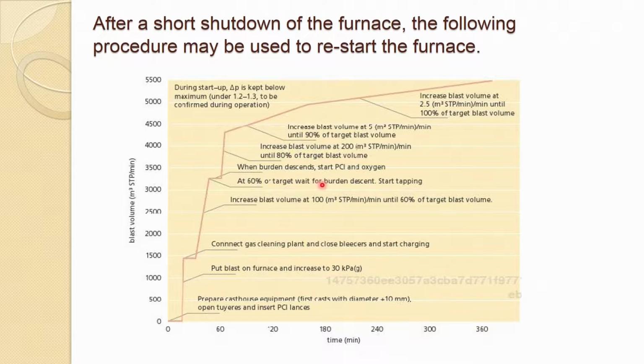So, at 60% target, wait for the burden descent, start tapping. When the burden descends, start PCI and oxygen at that time, and increase the blast volume to 200 meter cube per minute until 80% of target blast volume is reached, which is usually achieved in an hour or so.